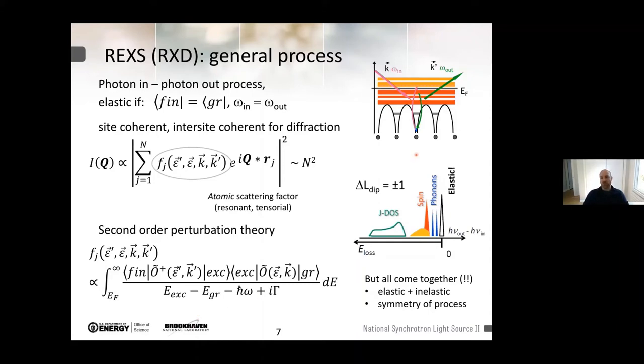relies on the photopromotion of a core electron to inspect empty states above the Fermi energy, and where the information on what is experienced by this electron, projecting its own state on the available states during this virtual process, is encoded in information that is retrieved out of the emitted photons, depending on their intensity, momentum, and polarization. Given that we want to deal with scattering and diffraction in particular, so in general staying in the elastic regime, the energy of the incoming and the outgoing photon have to be considered identical, and we will see that this is a little bit of an issue sometimes.